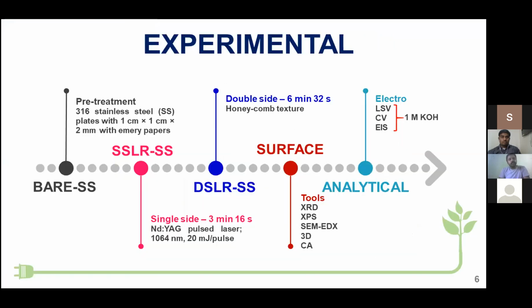316 stainless steel of size 1x1 was pre-treated with different grades of emery papers and ultrasonically cleaned in ethanol and water for 10 minutes. As a result, we get the pre-treated, pre-cleaned stainless steel substrate. That is the bare one, abbreviated as Bare-SS, which implies bare without any modification.